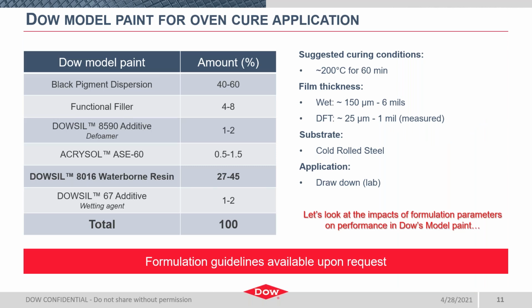This is a generic paint formulation, which was specifically designed to satisfy the performance needs for an oven cure application. As you can see, it contains most of your traditional high temperature paint components. 8016 is going to be the only resin in a lot of the data I'm going to share today, again, to address those ultra high temperature needs. The black pigment dispersion includes a blend of oxide functional pigments, which is very common and required for high temperature resistance. The functional filler we've included is silica. This is necessary for initial wet and dry adhesion, and then more importantly, post-heat adhesion.